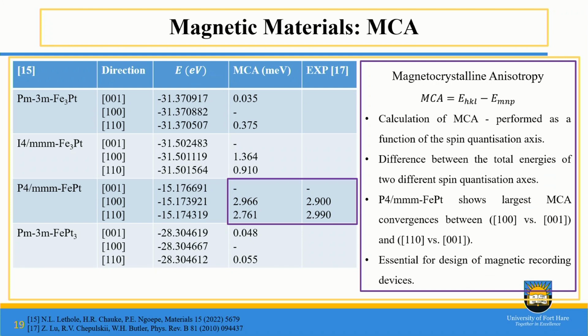The dashed ones mean that this one is the least energy, and the other ones were higher. We see that for the equiatomic structure, the magnetocrystalline anisotropy is in very good agreement with what has been found experimentally. This is the structure that has the highest MCA, or magnetocrystalline anisotropy, which makes it very essential for the design of magnetic recording devices.